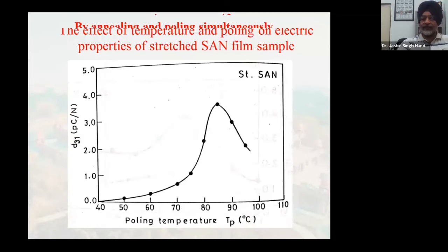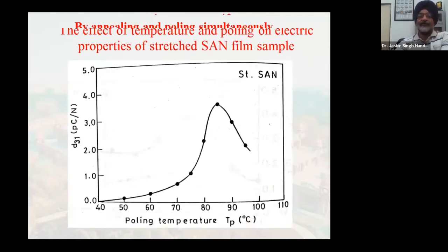So this is again at the same peak you have it for stretched styrene acrylonitrile. Here you had it for unstretched styrene acrylonitrile. The peak is at the same temperature, but the values of D31 obtained are different. Here they are around 1 picocoulomb per Newton in case of unstretched films, but for stretched films it is around 4 picocoulomb per Newton. So that is the beauty of things that we were able to improve the result. At least safely we can say up to 4 times.